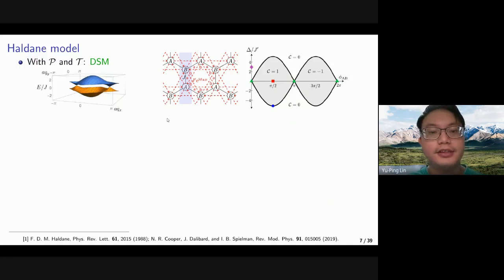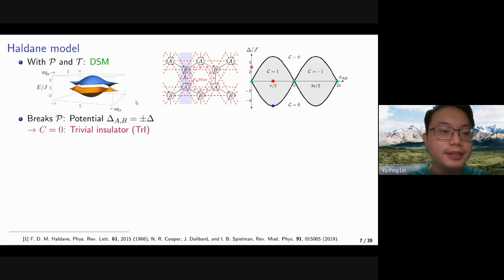So this is a figure for the graphene honeycomb lattice. If we only have the honeycomb lattice without any other additional things, we know that we have both inversion and time reversal symmetries. And if we look at the band structure, we'll have a pair of nodal points, which defines it as a Dirac semimetal. We can now try to break the symmetries. So first, let us try to break the inversion symmetry, which could be realized by introducing the on-site potential at A and B with an opposite sign. And if we make this kind of sublattice imbalance, we're breaking the inversion. And as we saw in the previous slide, it could lead to an insulator with Chern number 0, and so it is a trivial insulator.